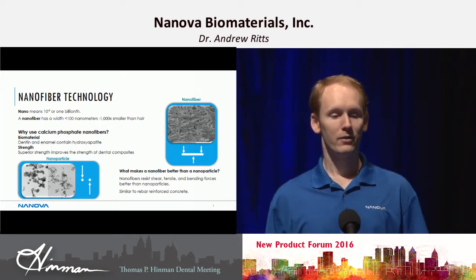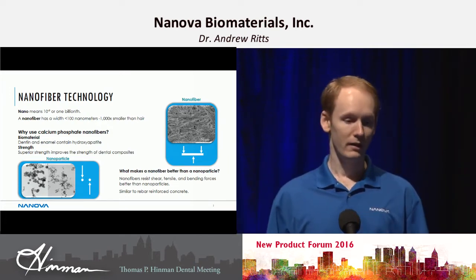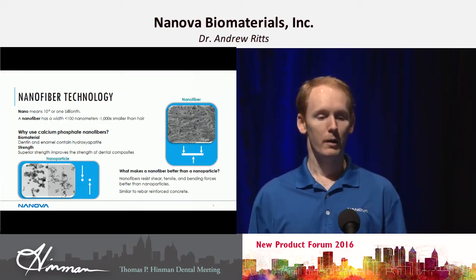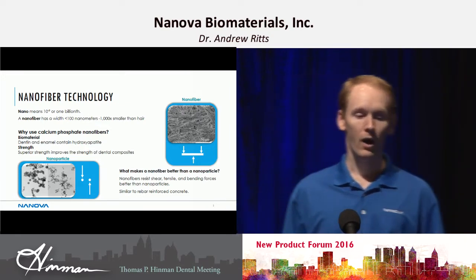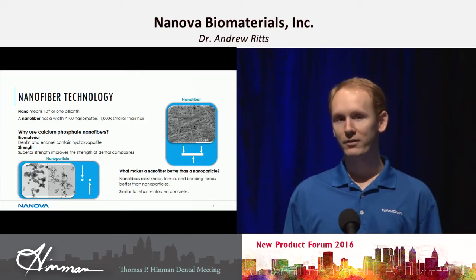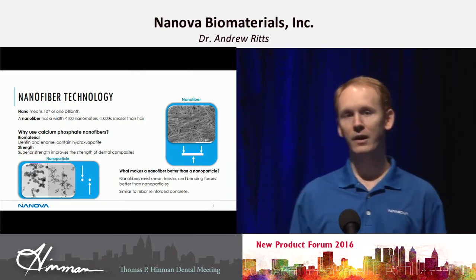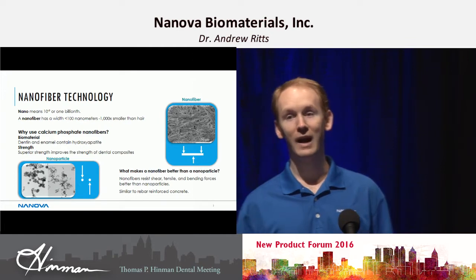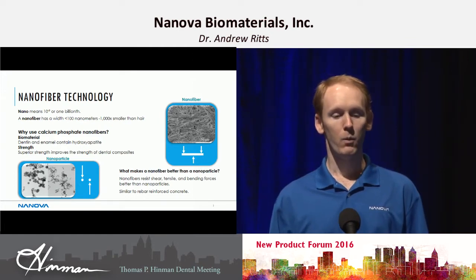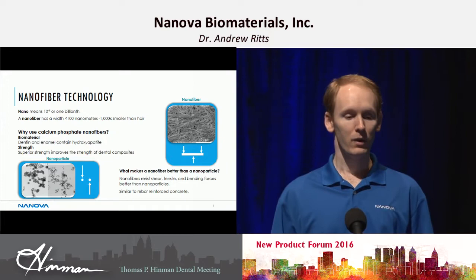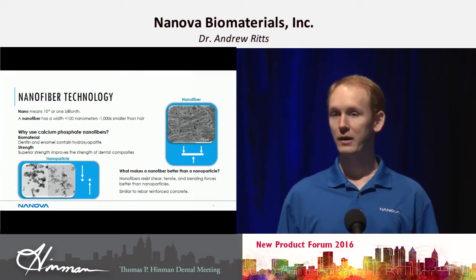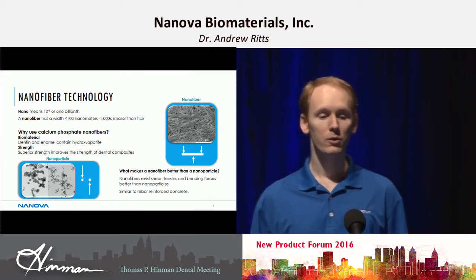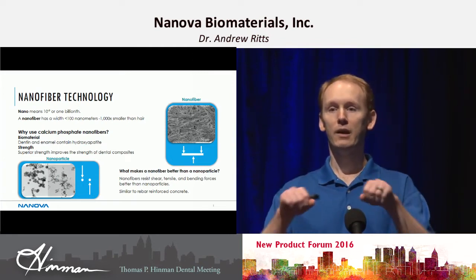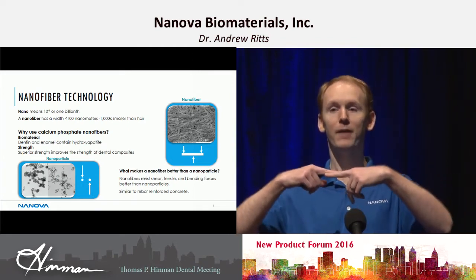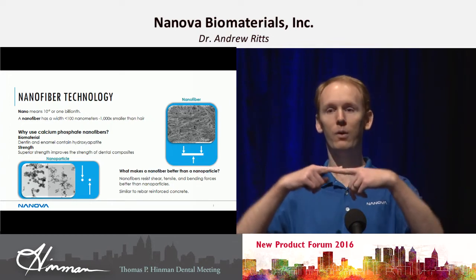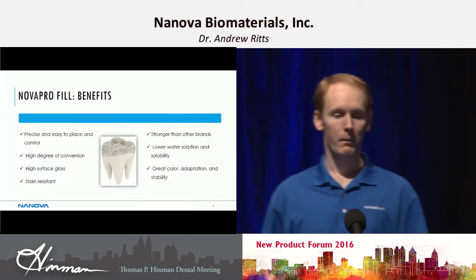Why do we use calcium phosphate nanofibers? It's a biomaterial. It's already in dentin and enamel, which contain the hydroxyapatite. Also, the strength is very high. Since we have a single crystal hydroxyapatite nanofiber, it's a very highly ordered structure, so it's a very high strength material. When we add it to our composite, the reason why it's better than adding particles, which everybody else in the industry uses, is particles don't do a very good job of resisting bending or shear or tension, whereas if you have a fiber, you can resist the tension or the bending or the shear much better than your traditional composite can.